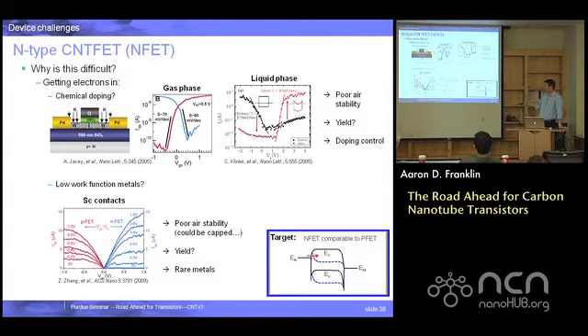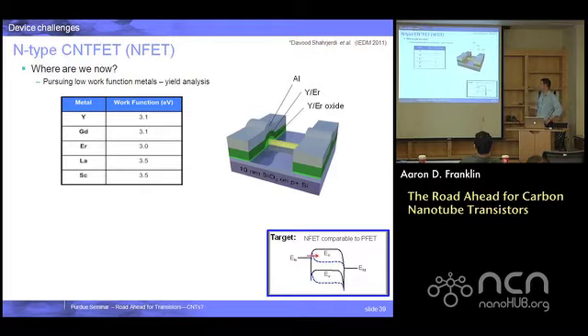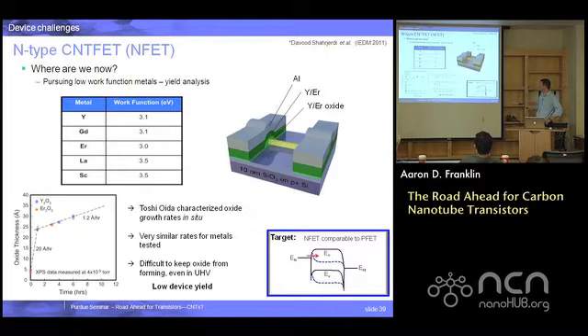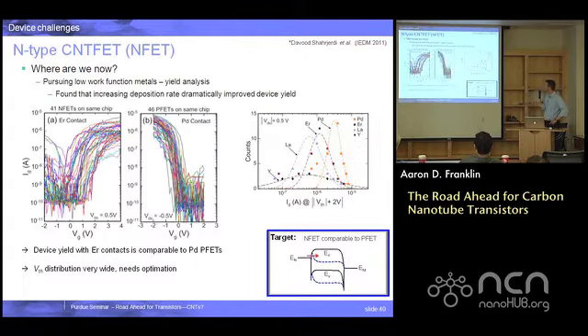And some people have shown good work on this. Mostly Lian-Mao Peng's group from Peking University in China have done great work on scandium and yttrium. But there's still this yield question of getting it to the place where it's comparable with what you get from palladium and the PFETs. So these are some results that we did and we've modified recently. I'll skip to this next slide to show some of the slightly newer data. This is using erbium. It hadn't been explored before, and one, we just wanted to be a little different, and two, it worked better than yttrium for us, so we decided to stick with it. But we wanted to look at this from a more technology perspective, and that is getting the yield higher. Not just getting a few really good devices, which we did, but looking at yield.